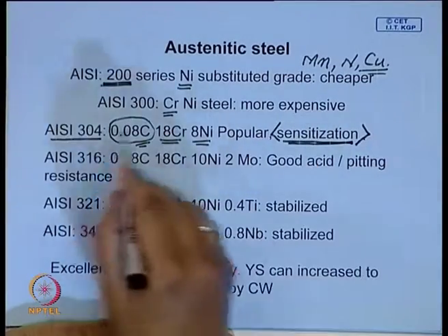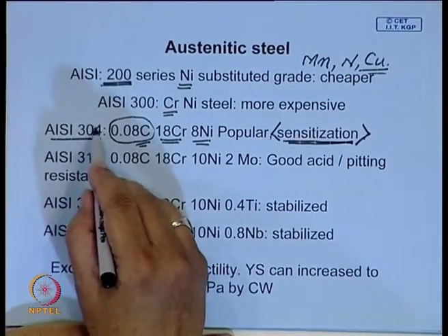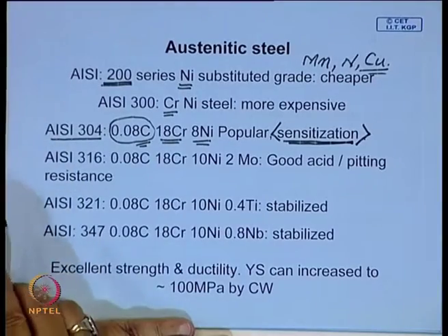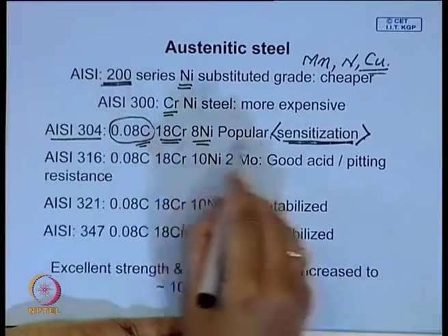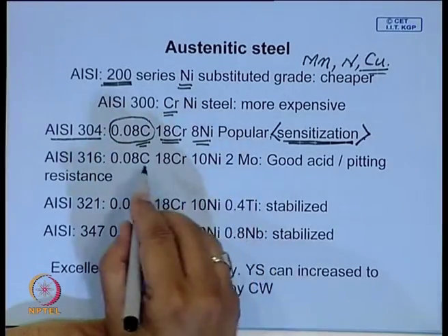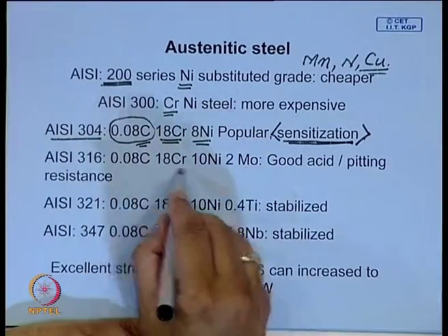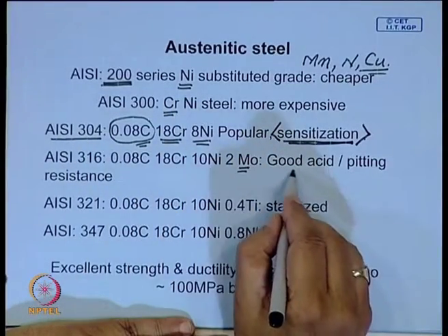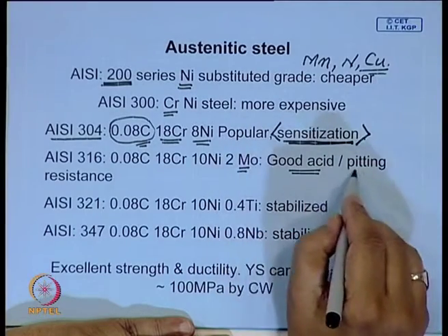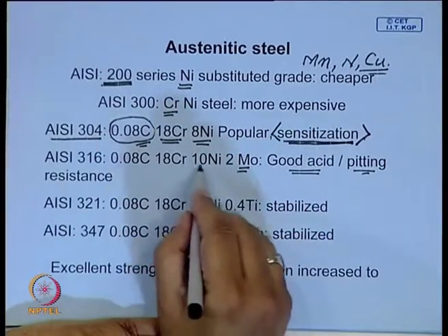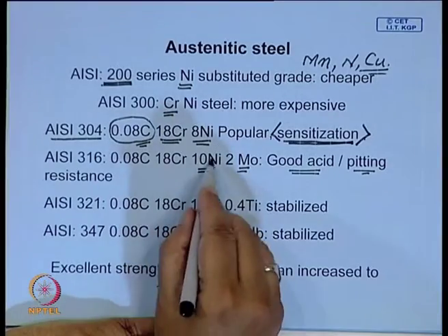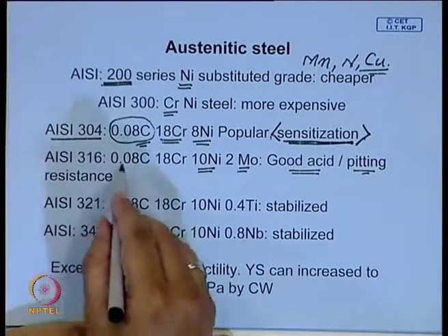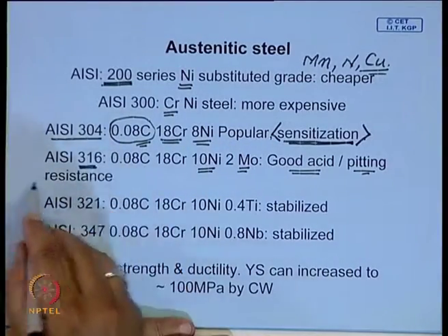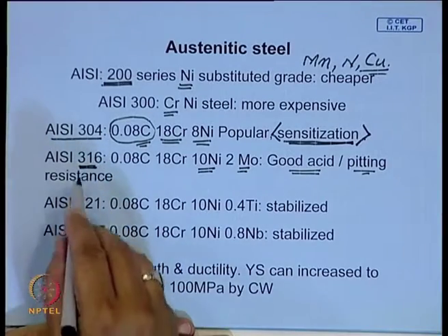Under this condition, these are susceptible to intergranular corrosion, and to avoid that, certain alloying elements are often added, like moly. It gives better acid resistance or pitting resistance. You have a slightly higher amount of nickel to give acid resistance. So, this is another popular grade, AISI 316.